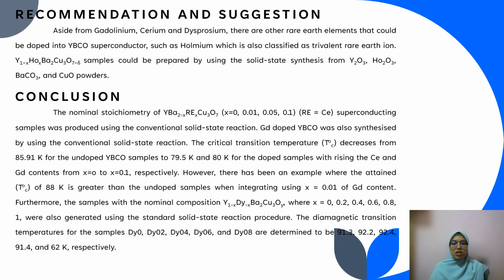In conclusion, cerium doped YBCO superconductor samples were produced using the conventional solid state reaction. Gd doped YBCO was also synthesized by using the conventional solid state reaction. The critical transition temperature decreased from 85.91 K for the undoped YBCO sample to 79.5 K and 80 K for the doped samples, with rising Ce and Gd contents from x equal to 0 to x equal to 0.1 respectively.